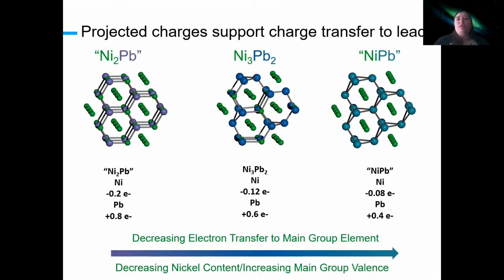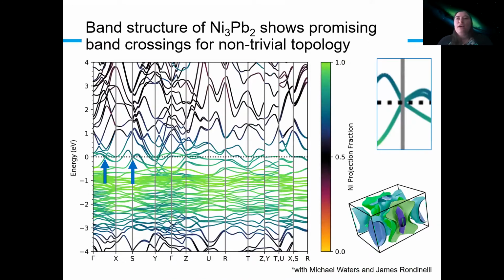In other words, we have a decreasing electron transfer in the main group, meaning we have a decreasing nickel content with increasing main group valence. You need fewer electrons to complete your octet. So it was pretty exciting to me that that held true as you explore the different pressure regimes. One of the final things that we were interested in looking at with these materials is that this material can be recovered down to ambient conditions. So what might its properties be?